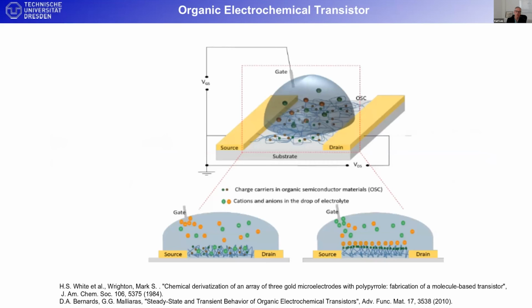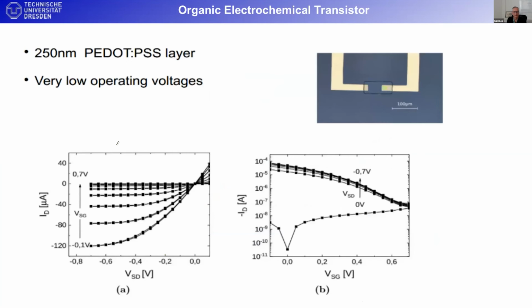However, another point I want to make is that organic flexible electronics is based on carbon-based materials, which is closer to the biological body than other materials. And furthermore, you can actually operate these transistors also in an electrolyte. You can use the electrolyte here to gate a polymer transistor. This is the so-called organic electrochemical transistor, which is known actually since many years, invented in 1984. But in the past few years, these transistors have been dramatically improved. This is a very simple example of such a transistor. Basically, it's nothing else than a little p-doped polymer, conductive polymer layer between the source and the drain, and by contacting an electrolyte on top, you get this, as you see, a very low voltage operation of this device.